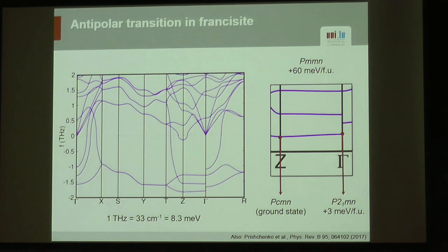And when you condense the two phonon modes, you find here a polar phase and here the antipolar phase. This is Pcmn, this is just 3 meV per formula unit higher, which is essentially nothing, okay? So it's really nearly degenerate, so this also looks very good. This is Jorge's calculation, but this was also published before, so it's not really new.